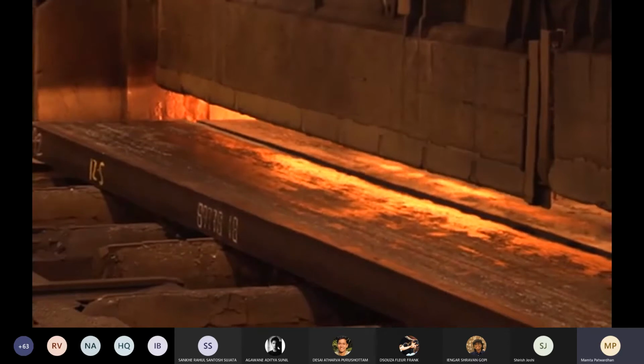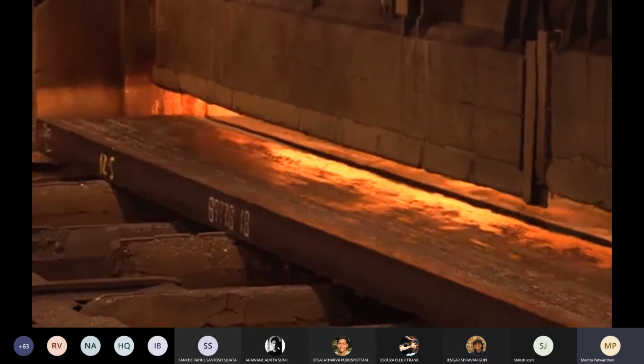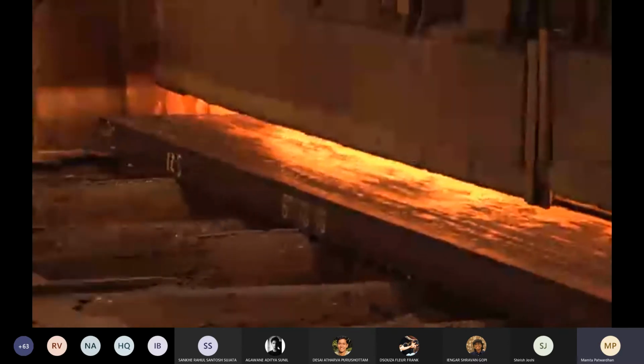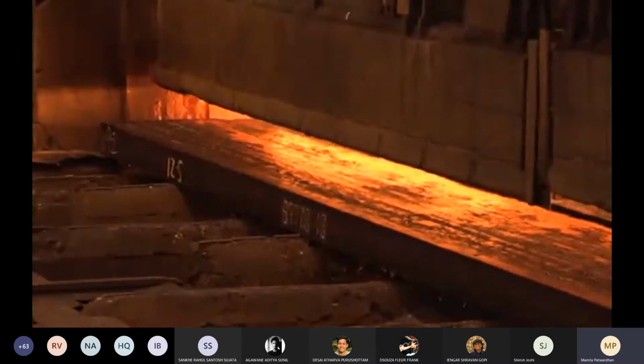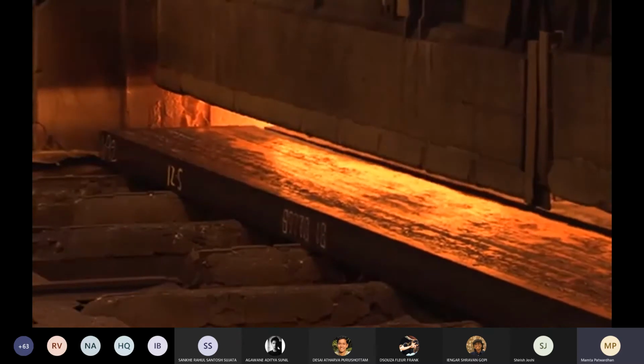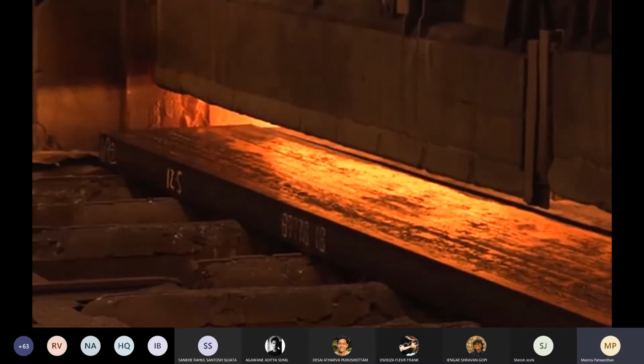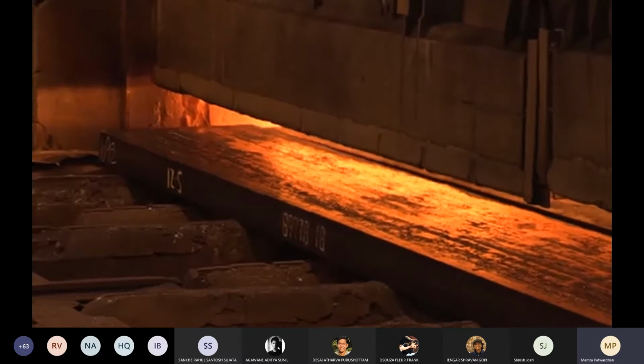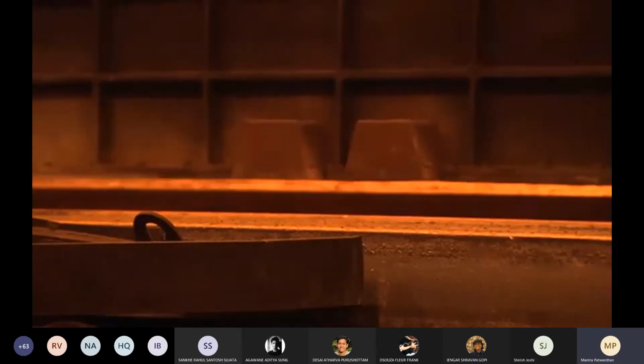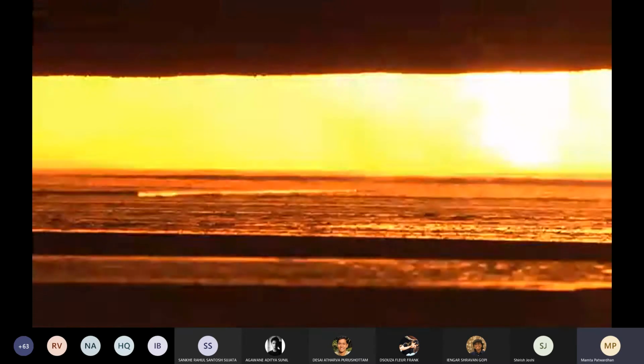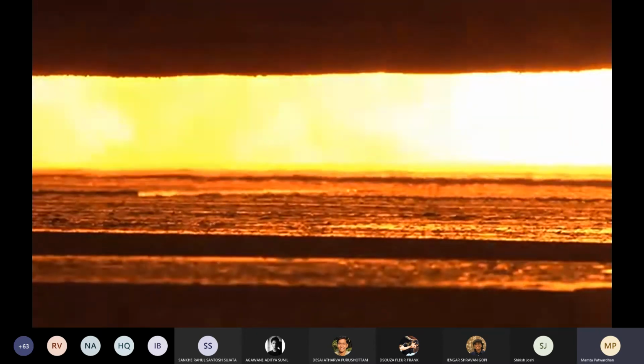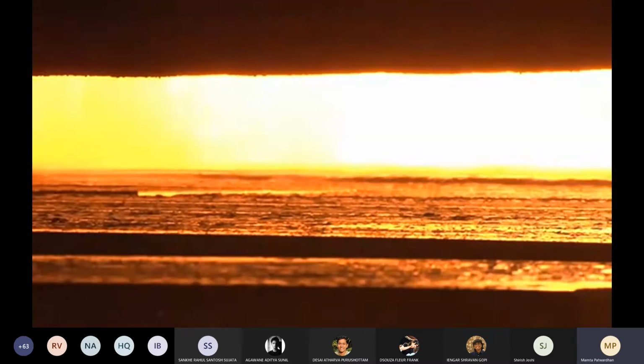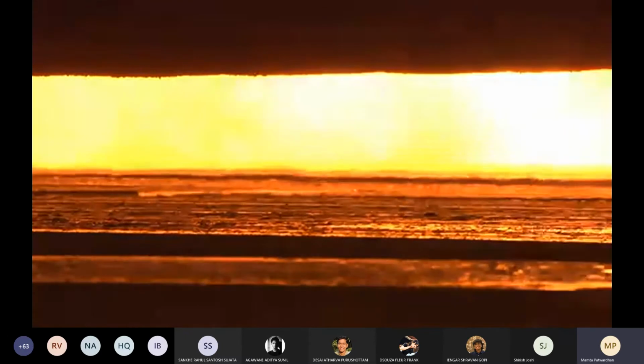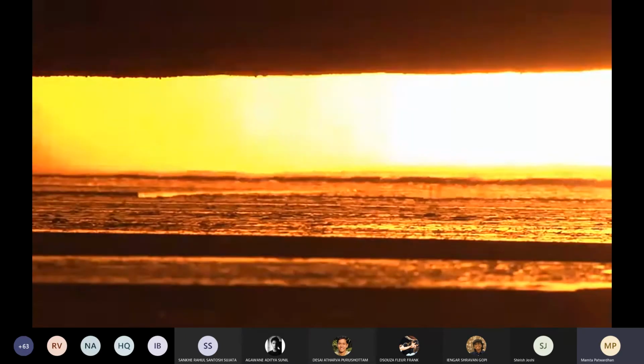These furnaces heat the material to about 1200 degrees centigrade. 2 walking beam furnaces feed the material through the oven. The heating is especially important as it affects the properties of the material. If the material is not sufficiently heated, incorrect material properties will arise. This is due to carbides and nitrides failing to dissolve.